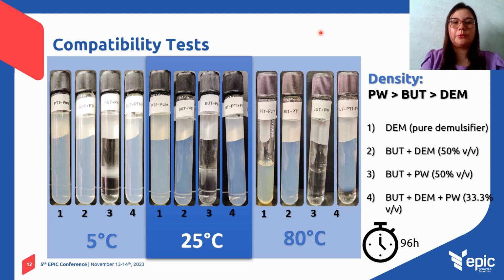From these tests, we can conclude that the butylglycol is not compatible with produced water, as they form separated phases, indicating that they are not totally chemically compatible. However, butylglycol and the demulsifier are homogeneous at all these conditions, indicating they are totally chemically compatible, with just one phase along the period. This allows us to conclude that the chemical compatibility hypothesis for clogging formation can be discarded, unless there is backflow of produced water in the chemical injection valve.